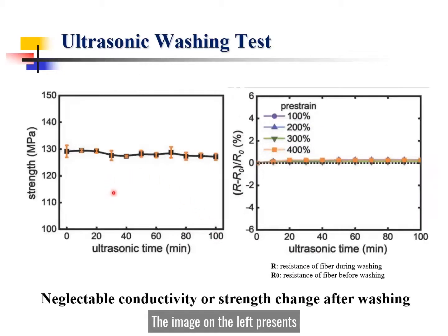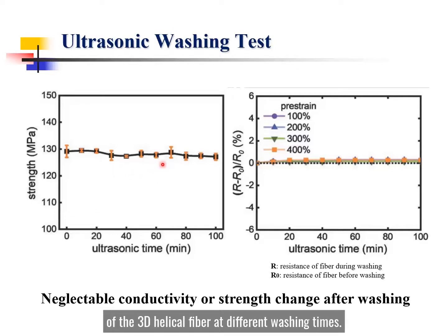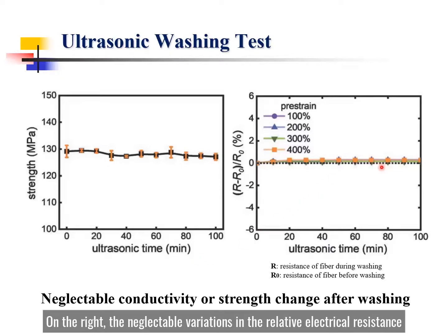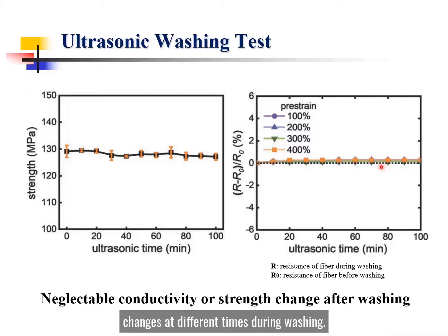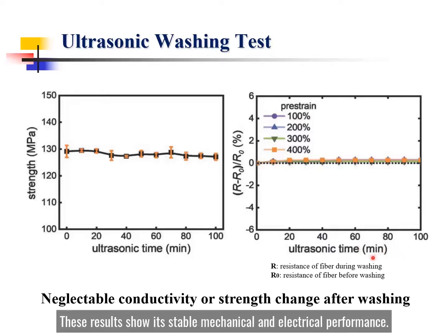The image on the left presents the small variation in the mechanical strength of the 3D helical fiber at different washing times. On the right, the negligible variations in the relative electrical resistance trends at different times during washing. These results show its stable mechanical and electrical performance.